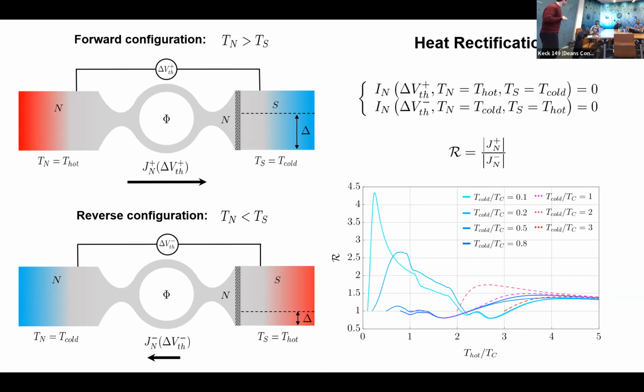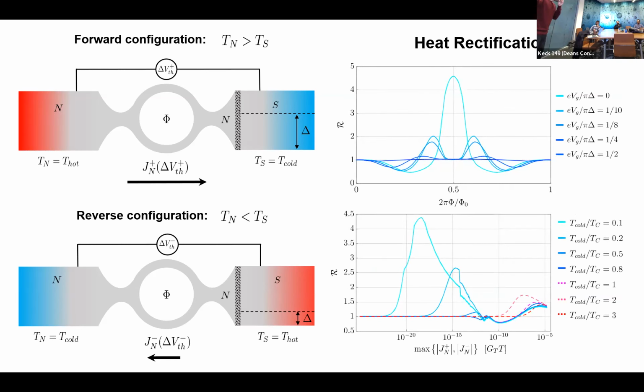One other thing is that if you have a very small current, generally you have very large rectification, which diverges in other systems, right? Which I don't think you see here. Indeed, when the rectification is maximal, you have very, very small heat current. But nothing is diverging. Because you're exploiting the real superconducting nature of the superconductor, the heat fluxes are not so high, and indeed the values of the heat current are pretty small.